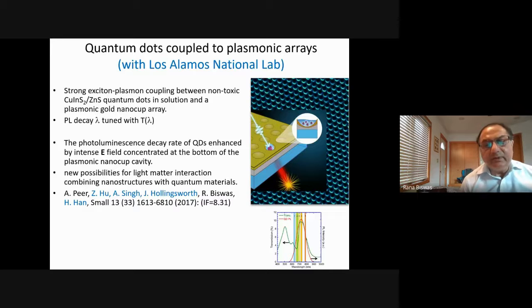So while I was presenting such results at conferences, I was contacted by the group at Los Alamos National Lab, which is one of the experts in fabricating quantum dots. And the basic idea in this figure you can see is that if you put a quantum dot inside the structure, and the quantum dot sits in a solution environment, you can tune the photoluminescence wavelength exactly with the transmission wavelength of this whole array. So you see this in red, the photoluminescence of the quantum dot. And our collaborators used these copper indium sulfide, zinc sulfide quantum dots in solution, which have a maximum of 700 nanometers in their photoluminescence.